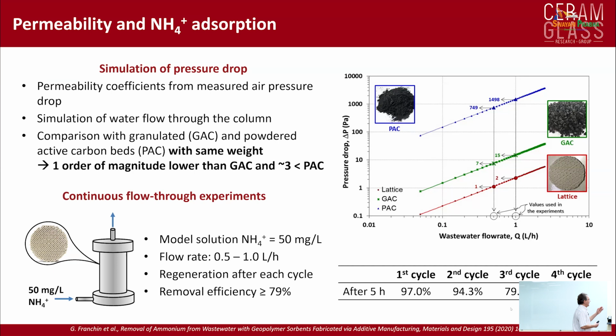I mentioned that we wanted to use these components for removal of pollutants from water. In this example, I'll show you some experiments that we carried out in collaboration with some colleagues for eliminating ammonium ions from water. And you can see that we were quite successful, and the material kept a reasonable performance after a certain number of cycles.